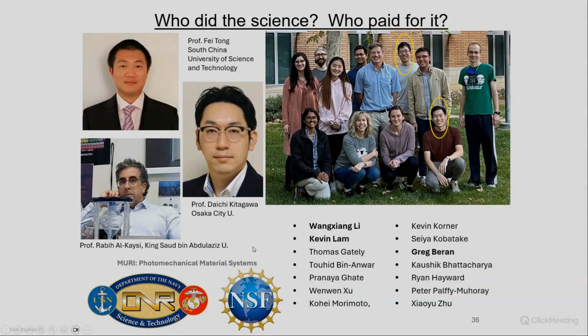Yeah. Another question by Hans Bettinger. How dependent are local and global crystal properties on the density of crystal defects? Yeah, so great question. And again, the short answer is we don't know. There is variation between crystals, although we've gotten rid of a lot of that, especially with the oscillating crystals. So our thinking is that it's not that dependent on the defect density, unless you have very high defect densities, because we do get similar behavior. The real variation in behavior is due to, we think, the crystal morphology.